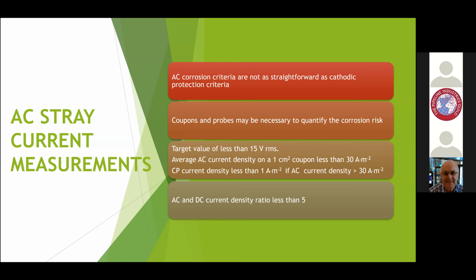The next thing we have to do is to measure the current density on a 1 centimeter square coupon. And to do this, we connect a coupon to the pipe, normally via an above ground test post, so that the coupon is experiencing the same electrical characteristics as the pipe. And we can measure the coupon current and the coupon potential very easily. And we give a guide of saying it should be less than 30 amps per square meter. But there is a relationship with the cathodic protection current density that we put onto the pipe. So that's only valid under certain circumstances. And then you need to keep the cathodic protection current density to less than 1 amp per square meter if the AC current density is greater than 30 amps per square meter.